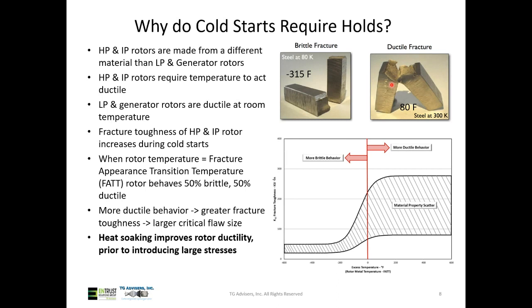So what we're trying to do, and why we require holds on many cold starts, is we want to keep that rotor at a low stress state. So typically that means holding at a speed below rated speed for a period of time to gain temperature such that the material properties improve, such that I'm not at risk for this burst condition.